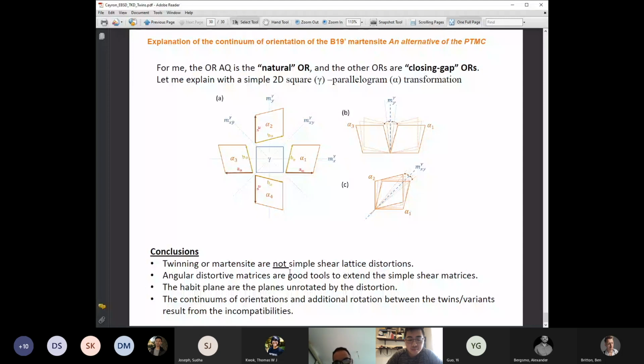And even if you look at twinning, deformation twinning in magnesium, if you look at the pole figures, you will see that you have not a point in the pole figure, but you have tiny lines, tiny arcs of circles. Yeah. And these tiny arcs of circles are exactly due to this effect, that you need to accommodate the orientation between the parent and the daughter.